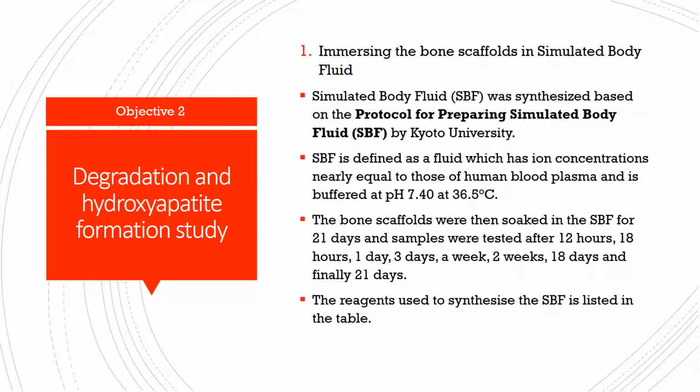The bone scaffolds are soaked in simulated body fluid for 21 days, and samples are tested at intervals of 12 hours, 18 hours, 1 day, 3 days, a week, 2 weeks, 18 days, and finally 21 days. The reagents used to synthesize the SBF are listed in the table.